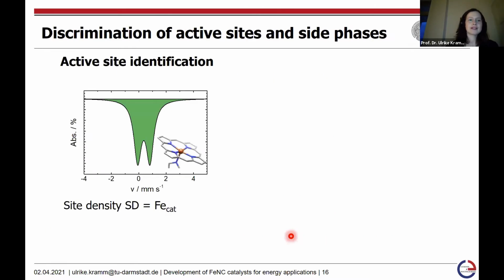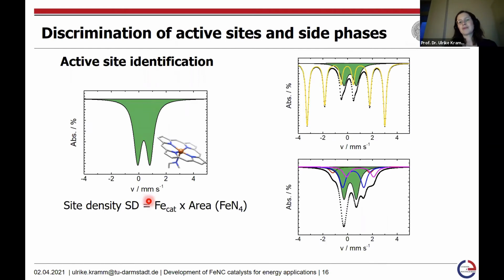Based on this, let's say we would have the ideal case and we would only have a doublet. Then, of course, the site density basically equals the overall amount of iron that we have within our catalyst material. Unfortunately, based on the heat treatment that we perform, it's more often that we have an overlay of different species. Sometimes we even see some sextets within our catalyst materials, or we might have some additional doublets, but only a distinct quantity might be related to the activity. And in that case, of course, we need to multiply the iron content with the absorption area that is associated with the FeN4 environments that we assume as active sites in these types of catalyst materials.